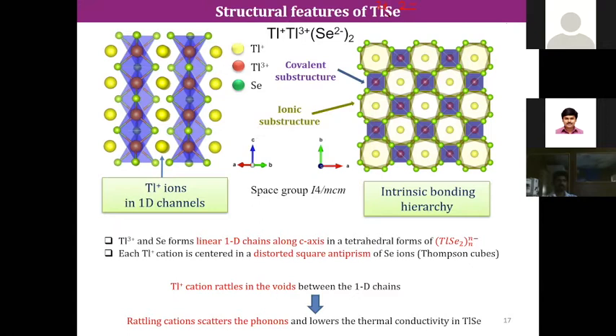Okay, so now we have done low temperature heat capacity, because we have to show it by experiment. Theoretical support is good, but that is not enough. We have to do an experiment to show this low energy optical phonon modes. Low temperature heat capacity is a simple experiment, but it can give you a lot of information. This is C over T squared, taken from 2 to 30 K. Generally this heat capacity obeys the Debye T cube law. But the Debye model, which generally describes normal solids, cannot fit this low temperature heat capacity.